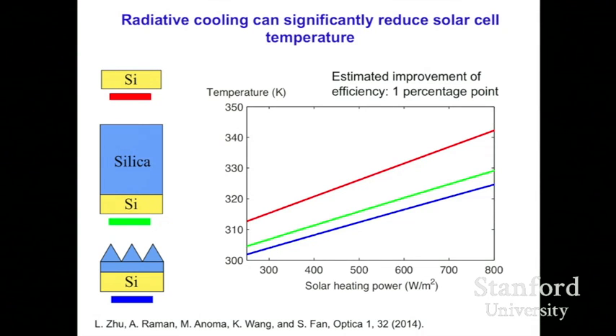So with that, we can compare the performance of 3 different structures: a silicon layer by itself, a silicon layer with a thick silica layer on top, and a silicon layer with a structured silica layer on top. And we plot the temperature of these structures as a function of heating power. So on the order of 800 watts per meter square of heating power, what you see is that putting a thick silica layer on top reduces the overall temperature by about 15 degrees Celsius, theoretically.